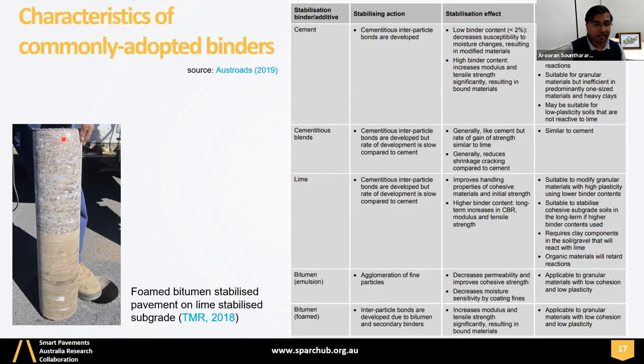So there is a core sample extracted from a foam bitumen pavement, just for your information. It is from TMR. TMR means Transport and Main Roads Queensland. This pavement was constructed as a flood resilient pavement. That means foam bitumen performs excellently under flood conditions. Queensland receives a lot of flooding events within a year. Therefore, they are hungry for flood resilient pavements, and foam bitumen becomes a more effective solution for them. There is a core here. It's about 255 millimeter depth of foam bitumen pavement and natural subgrade stabilized with lime. So this is a typical visual appearance of these two layers.